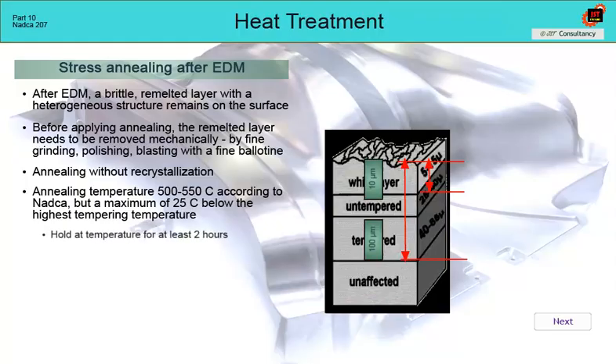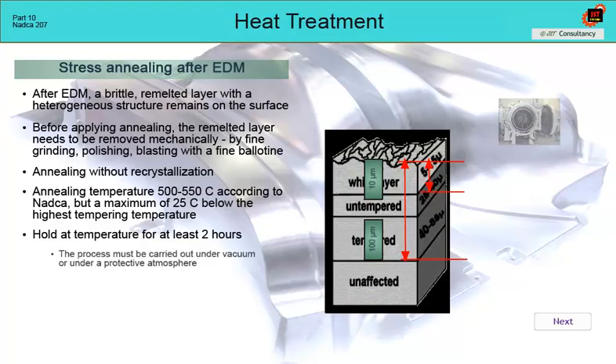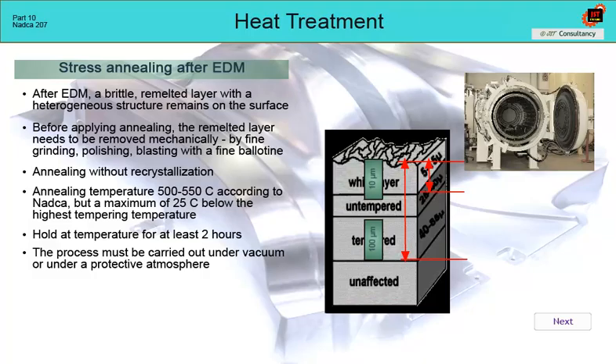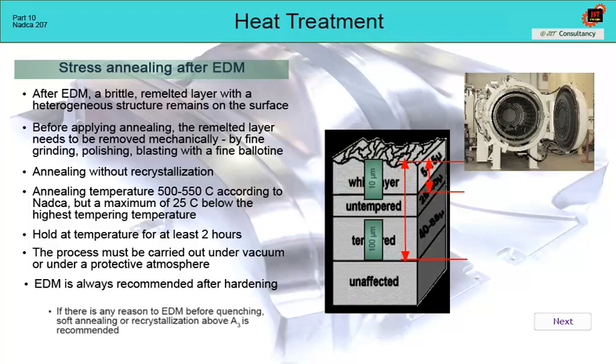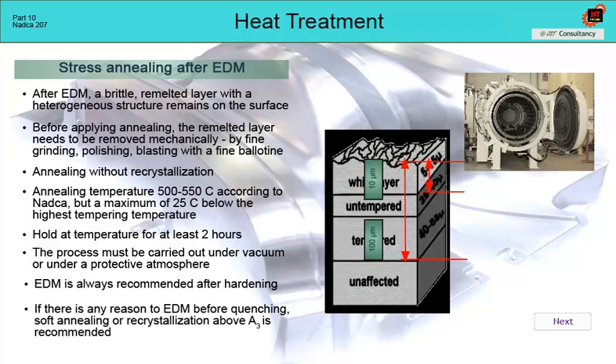The holding time at temperature is usually at least 2 hours, and can be extended depending on the size of the die. Since at this stage the part is already almost finished, annealing must be strictly carried out in a vacuum furnace or under a protective atmosphere. EDM before hardening is not recommended. If it is necessary, then the layer needs to be treated as before, or even better. Instead of annealing to remove stress, include soft annealing or annealing with recrystallization above A3 temperature before hardening.